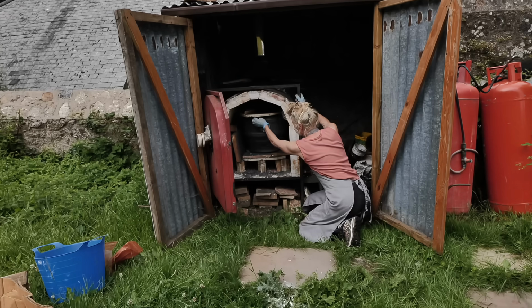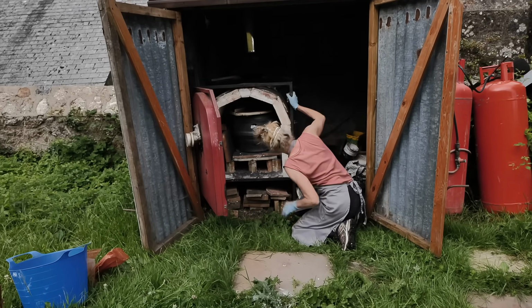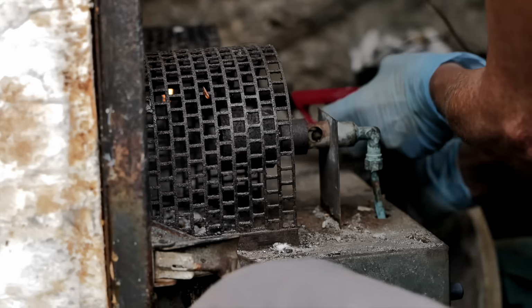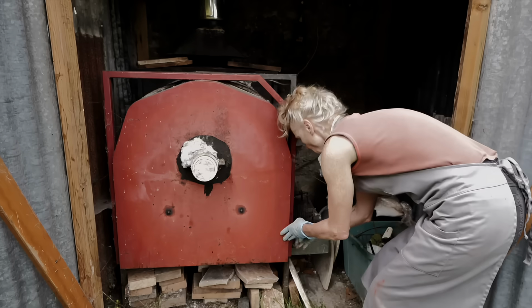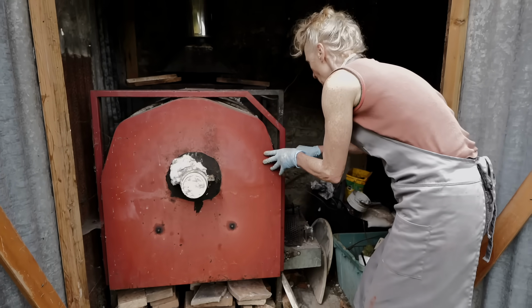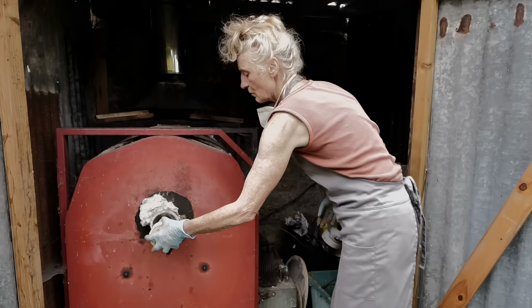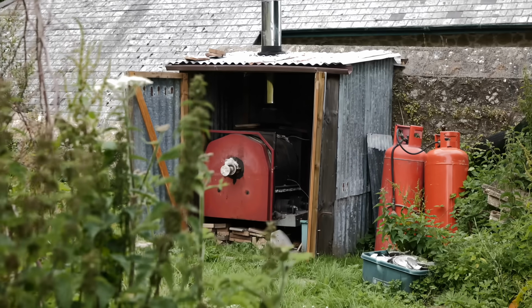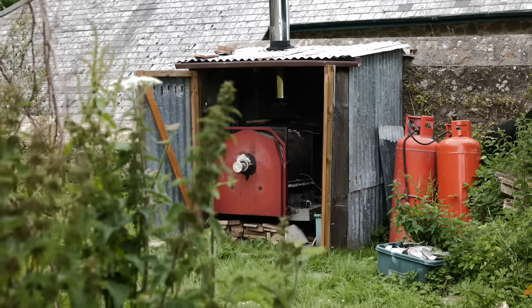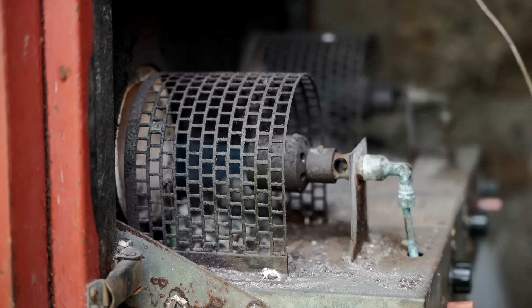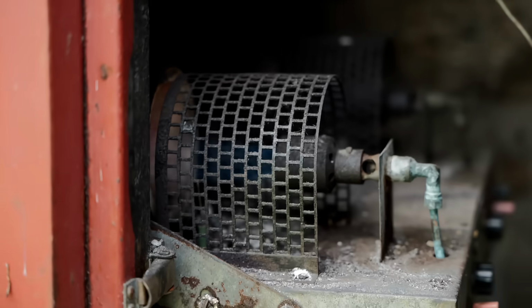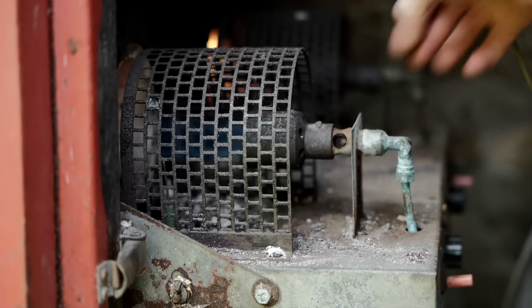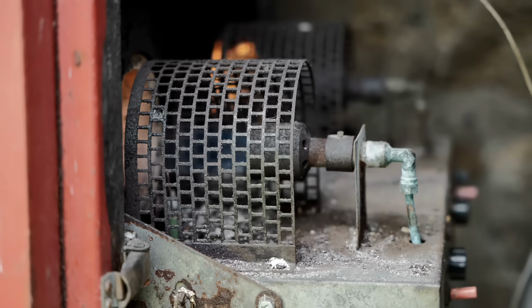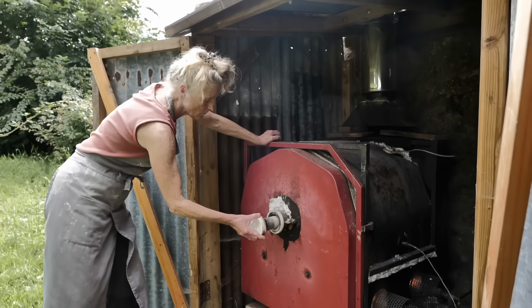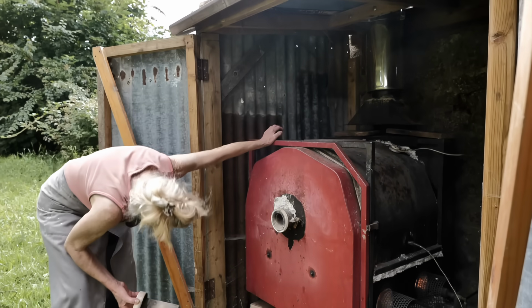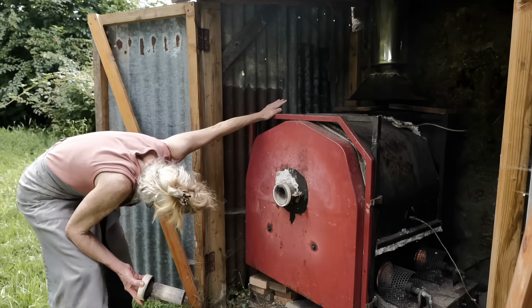There is airflow from the top because the top of the saggar is not completely flat. I want some air, but not too much. Once the kiln is lit, the front bung is halfway out, so some oxygen is going in, and I keep the burners down as low as I can. Around 530 to 600 I will start reducing it lightly, which in this kiln is to slightly close off the chimney and slide the damper on the burners, and I just give it some light reduction. The saggar creates its own reduction, but I add some reduction with my kiln.